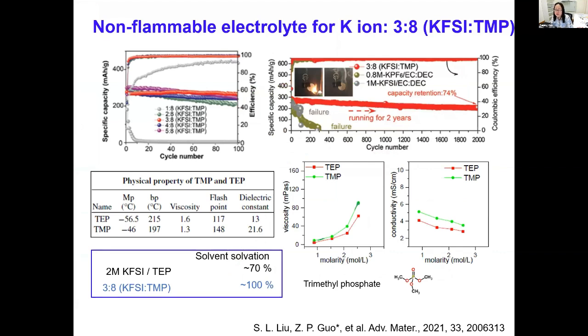So basically, by using the fire retardant as a single solvent, we can achieve a non-flammable electrolyte with quite good electrochemical performance. So how can we further improve the performance? Apparently from the previous work, we found only 70% of the solvent is associated with potassium. If we can achieve 100% solvation, then we can 100% prevent the decomposition of the solvent and further tune the chemical composition and morphology of SEI.